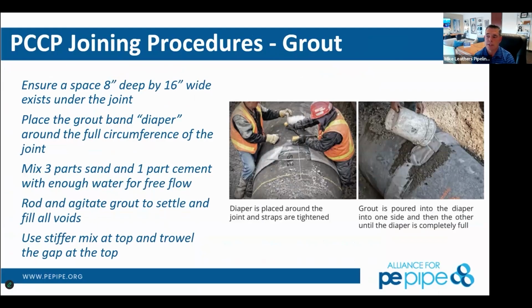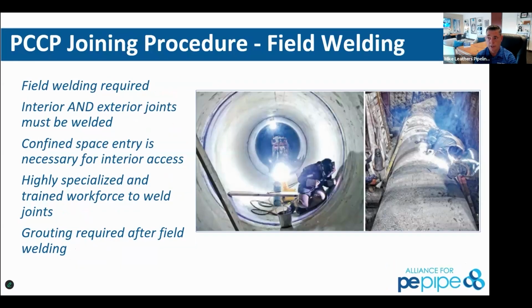So besides getting this pipe to the job site and getting it into the trench with proper bedding, there's also a great amount of risk that the welds are done correctly. There's been a lot learned about welding and how to test welding, and then the grouting, which is also extremely important and is usually done by the lowest paid, lowest experienced guy to apply grout. Are you sure they're protecting all the welds? Are the welds actually correct? And then you're protecting all that steel and all the joining mechanisms from corrosion possibilities. And you can see this happens on the interior and exterior of these types of pipe. Next.